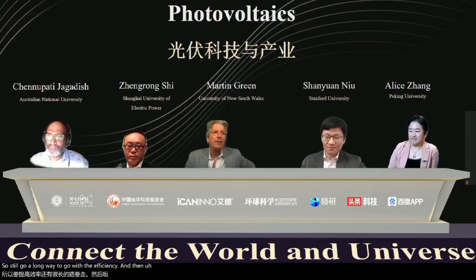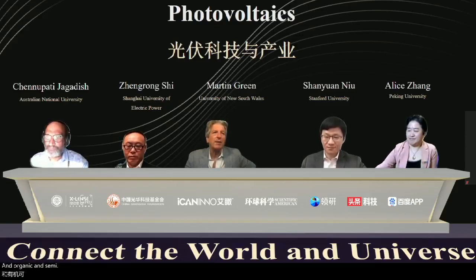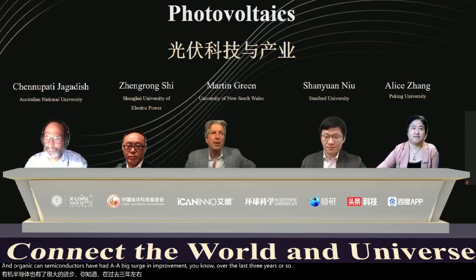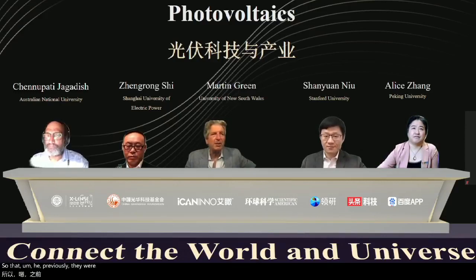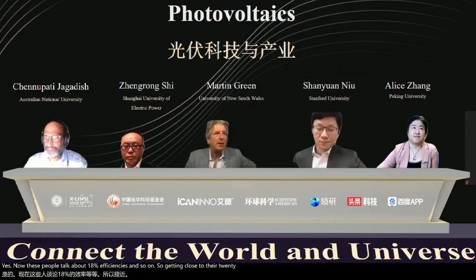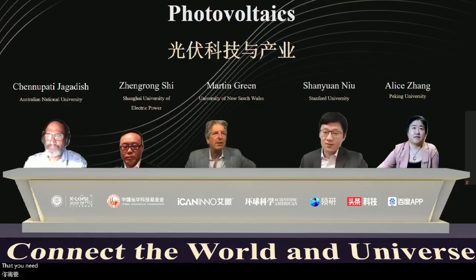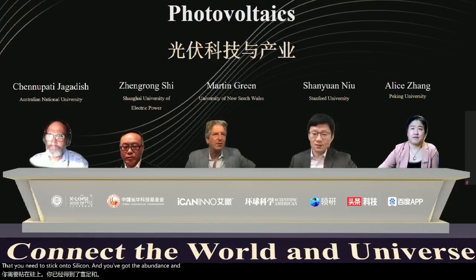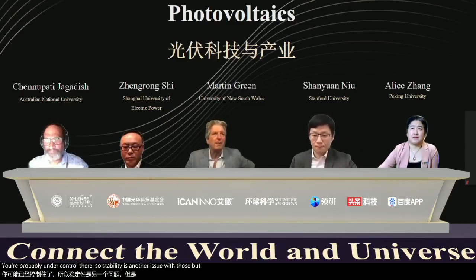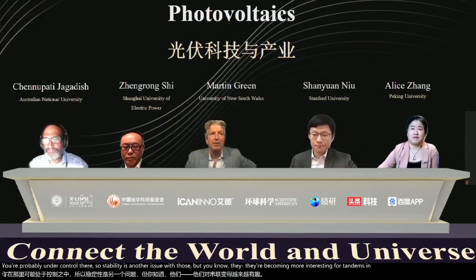And then there's a lot of less developed materials that people are interested in as well. Organic semiconductors have had a big surge in improvement over the last 3 years or so. Previously they were too inefficient to think about in terms of stacking onto silicon, but now there are people talking about 18% efficiencies and so on. So they're getting close to that 20% level that you need to stack onto silicon, and you've got the abundance and non-toxicity properly under control there. Stability is another issue with those, but they're becoming more interesting for tandems than they were just a few years ago.